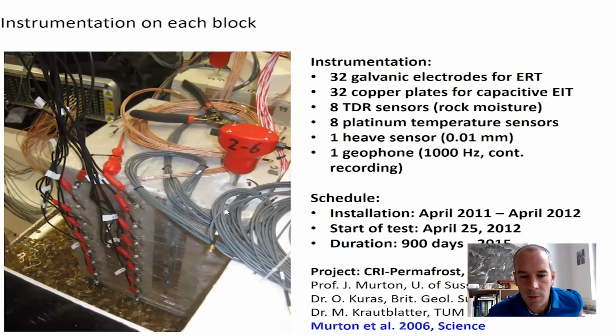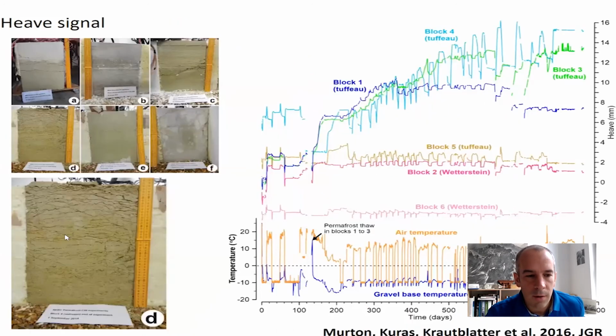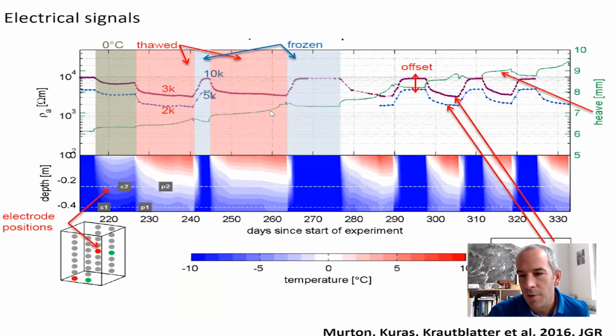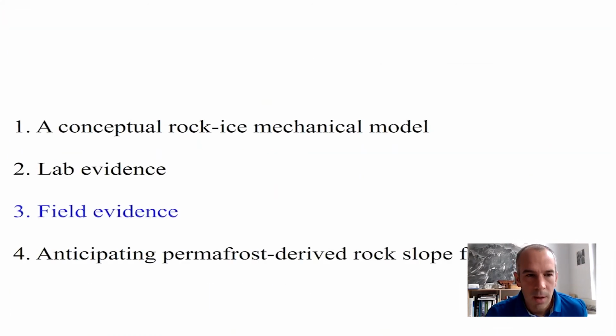Over 900 days of repeated freeze and thaw cycles in these rocks, you can see that this previously intact rock is entirely shattered. From the top to the bottom, you see all these cracks were induced by ice lenses that grew into it and caused cryosuction and ice segregation pressures and destroyed the samples. You see some of the samples had deformations in the range of 16 millimeters, which is quite a lot. But even the Wetterstein, that is a very tough limestone from the Zugspitze, had deformations in the range of 2 millimeters.